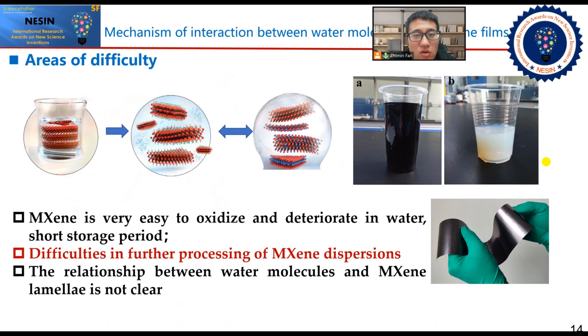As we know, the exposed titanium atoms on the surface of MXene obtained by etching the MAX phase are unstable and easily oxidize to non-conductive titanium dioxide in oxygen-containing water, resulting in its short storage period, which is a major problem that the industry urgently needs to solve at present. In addition, the MXene dispersion has a low concentration, which causes a large amount of water to be removed subsequently, making the process extremely difficult.